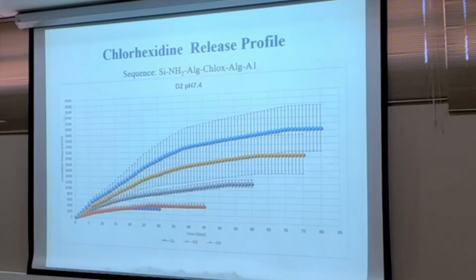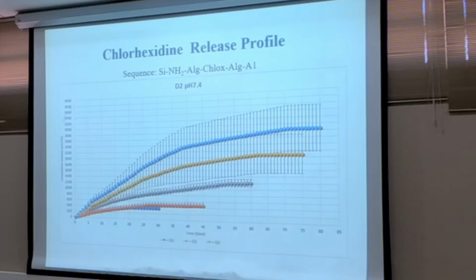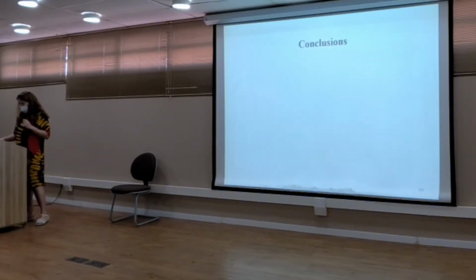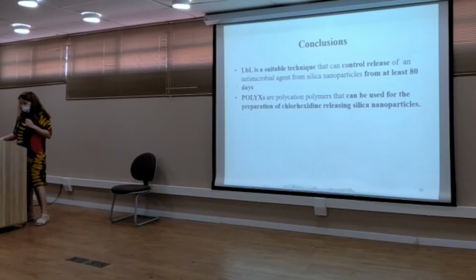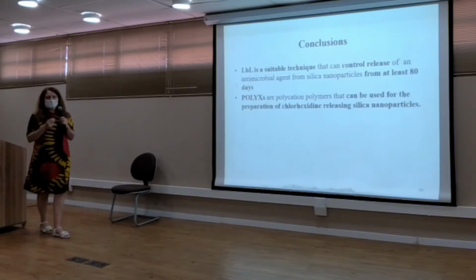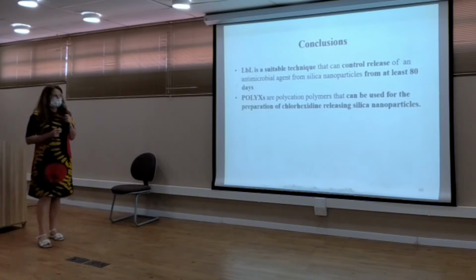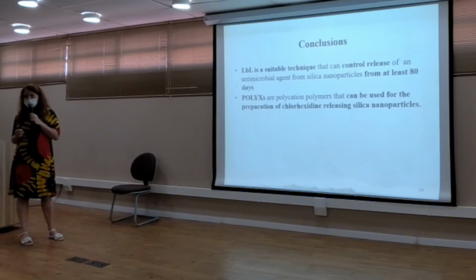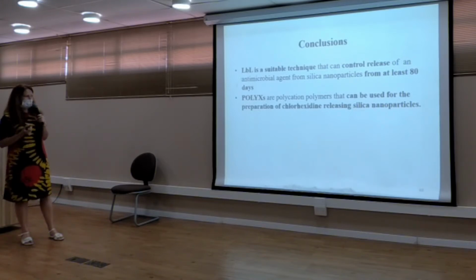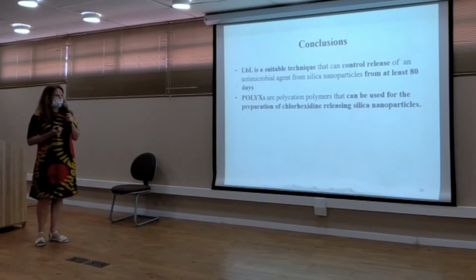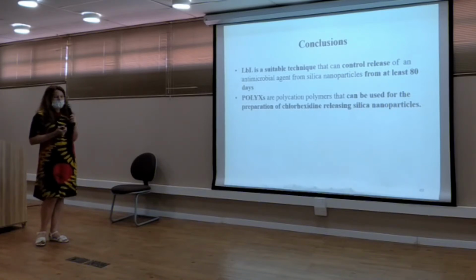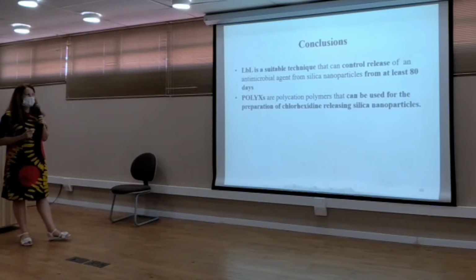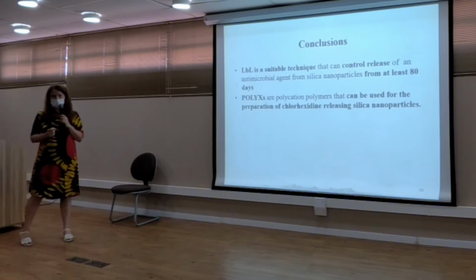Our hypothesis is that the charge of chlorhexidine is higher compared to gentamicin. So electrostatically, it is retained within the LBL construct better and for a long period of time. That's why we have such a controlled release. In conclusion, layer-by-layer deposition is a suitable technique to control release of antimicrobial agents. The example is from silica nanoparticles, but we could have other model carriers as well. In the case of chlorhexidine, it was for 80 days, and poly-X, as a polycation polymer, can be used successfully for the preparation of chlorhexidine-releasing silica nanoparticles.